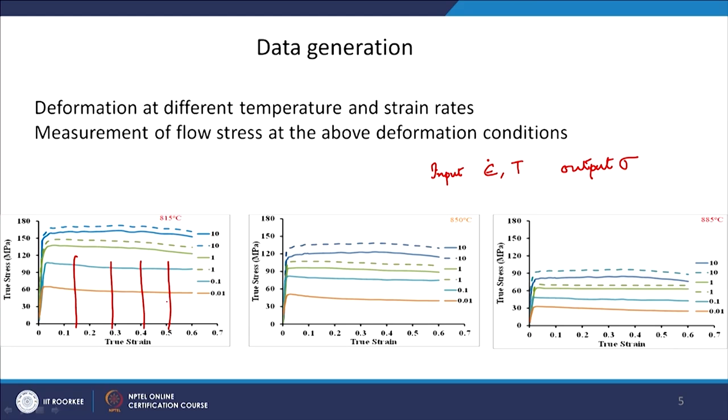Okay. If in your flow curve, you are also seeing maybe a strain hardening part. Okay. So, it is something like this, for example, then you should also consider strain in this term. Okay. Because your flow stress is continuously changing as a function of strain. But if it is a steady state, okay, then I would be mainly interested in strain rate and temperature. Okay. So, you should understand why most of the time you do not have strain in this constitutive equation when you are developing it for hot deformation. Similarly, if you develop for low temperature, okay, temperature below 0.4 of melting point, you will see that strain rate is not there, okay, because the strain rate dependence of stress reduces as you go to lower temperatures. Okay. So, you will see this effect that constitutive equations are changing as a function of temperature.